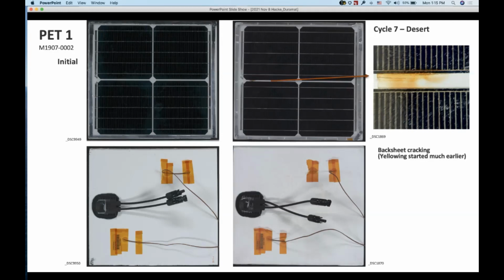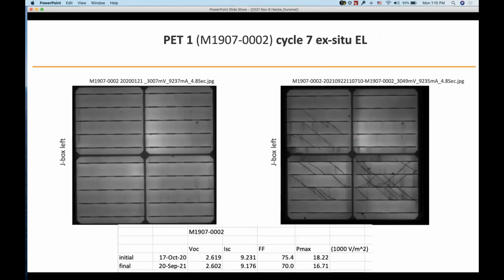Of course, the most obvious or the first answer that comes to mind is, well, it's a little bit hotter under the junction box because it provides some insulation as the light hits it in the combined accelerated stress testing. But we also wanted to see if there was anything else going on. So we look at the electroluminescence, and here we're looking at ex situ electroluminescence at room temperature.